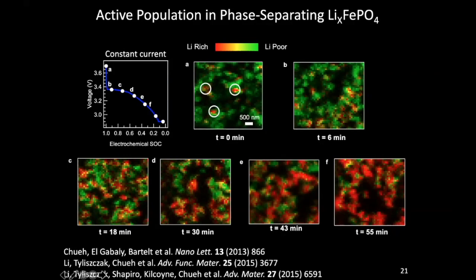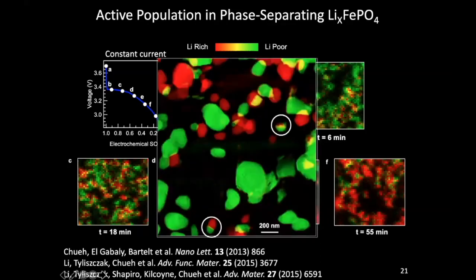So this is a movie that we have recorded of about 500 particles in lithium iron phosphate in a porous electrode. As we discharge, you can see that the discharging process does not occur very uniformly and occurs in hot spots. Okay, so you can see this in the dynamic video here. If I show you a static picture, you can also see that lithium is preferentially extracted and inserted only at select particles.